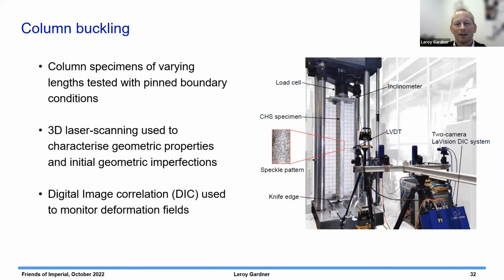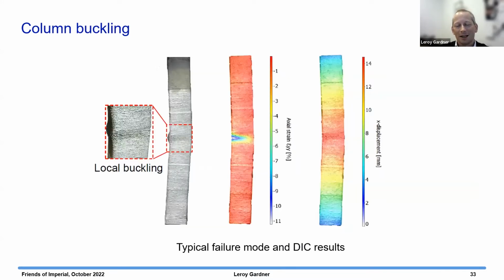And we did the same thing at member level. So in this photo on the right, this is a long column. It's about a 2-meter long column, a circular cross-section, and we loaded it between what are called knife edges, which allow the ends to rotate freely. So we put it in compression and it buckled. And again, using the digital image correlation system, you can get detailed information about how it's buckling. And you can see this localized effect as well as an overall buckle.